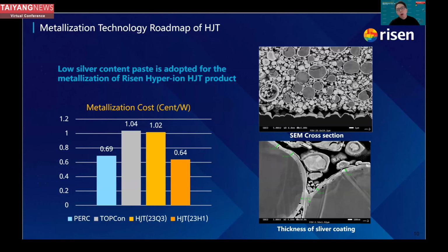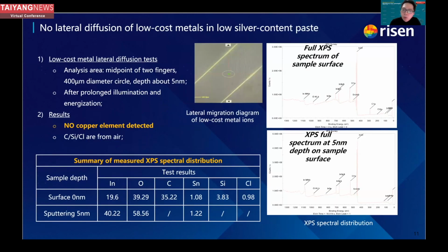There are also some worries when we are adopting low silver content paste, because there are other materials within this paste, such as copper. But we have done some tests to verify there will be no big effect. First, we did an XPS test to verify there is no vertical or horizontal diffusion of low-cost materials in the silver paste.